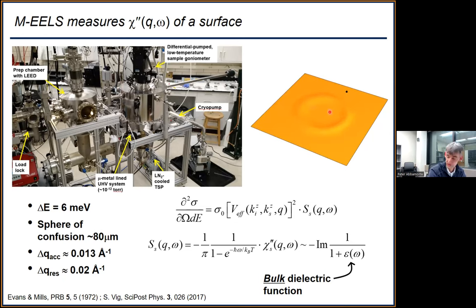So this is based on an old technique called HREELS, which maybe some of you have heard of. It's kind of gone out of popular use. So what we did is we basically made this momentum-resolved with really high accuracy. The energy resolution here is 6 meV in the measurements that I'm going to show you. It has a sphere of confusion of 80 microns. If you don't know what that is, it's fine. What it means is that we can measure the momenta with high resolution, high accuracy and high precision. Resolution means you integrate over a very small volume of momentum space. Accuracy means I know exactly where I put that volume in momentum space, so I can tell where I am.